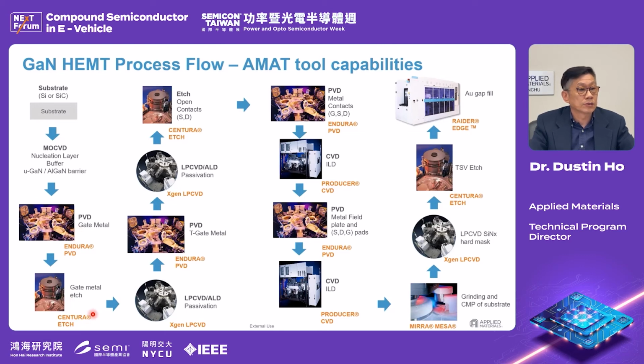Then the etch will be very critical for the selectivity of GaN and AlGaN, and we have LPCVD for the nitride passivation, and then PVD for the T-gate metal, then ALD, LPCVD isolation passivation, and then standard etch and the metal. PECVD for ILD, then our PVD for the source drain field plate, again another ILD, and we have the CMP for the grinding. Then we have the TSV for the backside etch, and we also have the plating tool for the gap fill.